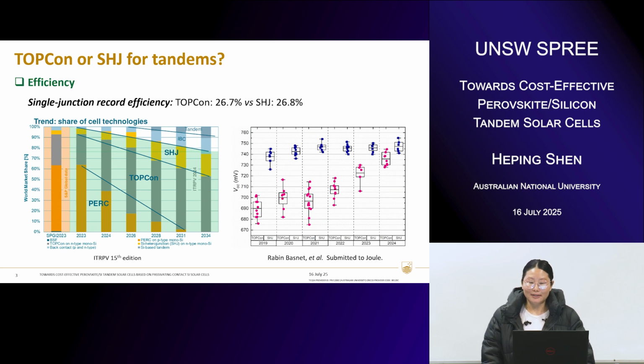For the TOPCon and silicon heterojunction, at the single junction level, the efficiencies are getting very close nowadays. If we look at the record efficiency, single junction TOPCon, which is 26.7, is very close to 26.8 by silicon heterojunction. Both of the cell performances were demonstrated by reliable, large PV companies. On the other hand, if we also look at the performance evolution of these 2 technologies, for example the open circuit voltage, we find that their performances are converging. The VOC values are very close, located in the 740 to 750 millivolt range. So it's clear that their single junction efficiencies are getting very close.